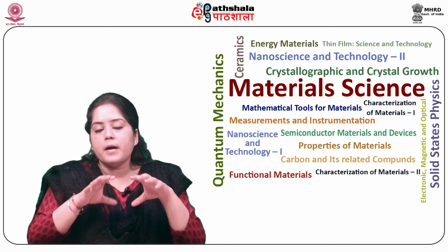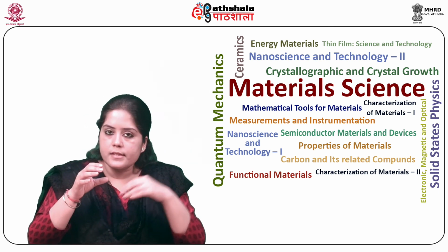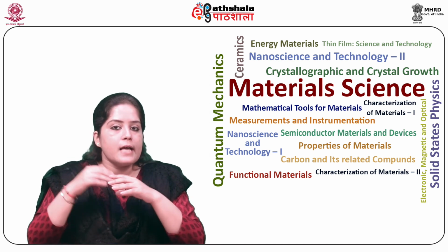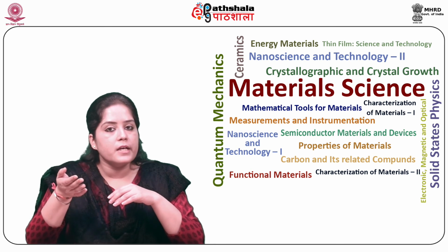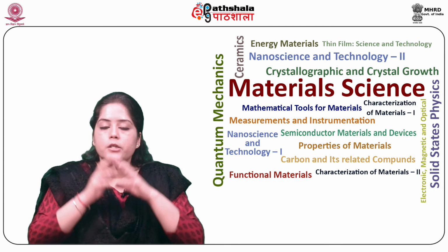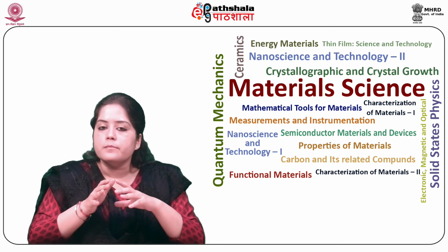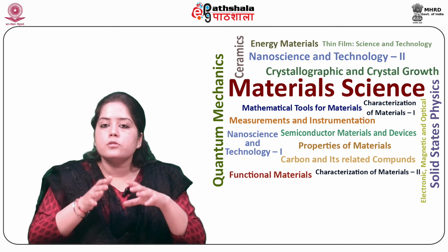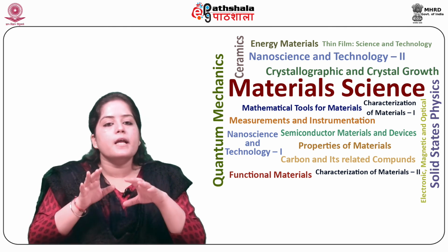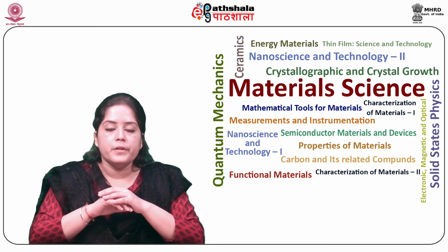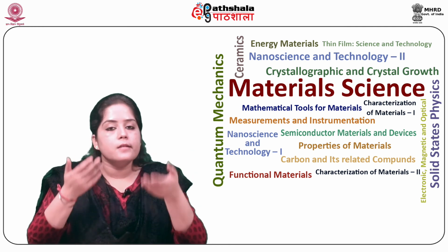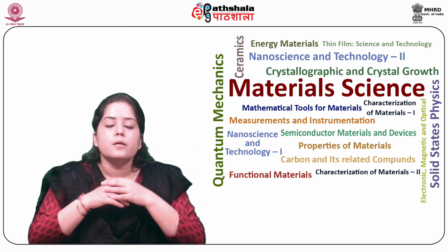So the effective path length depends on the angle of incidence. Therefore, for thin films, a grazing angle of incidence as high as 80 to 85 degrees from normal incidence should be used. And for thick films, an angle close to normal incidence is applied. So the most common applications of this technique are the evaluation of surfaces such as coatings, thin films, contaminated metal